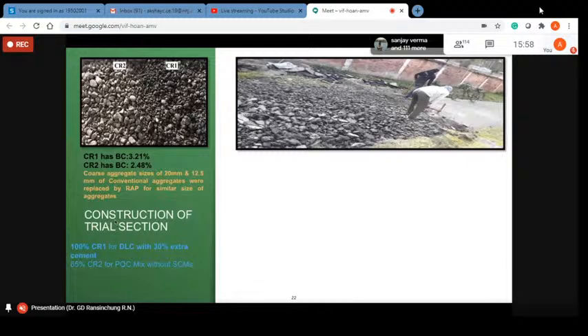Similarly, for PQC slab construction, we considered 65% using CR2, because it has comparatively cleaner aggregates in terms of asphalt content, but without supplementary cementitious materials. So the construction has taken place in this manner. The RAP material that we obtained was used in the DLC construction at 100%. And this is how the GSB layer was prepared, and the DLC layer is being cast here.